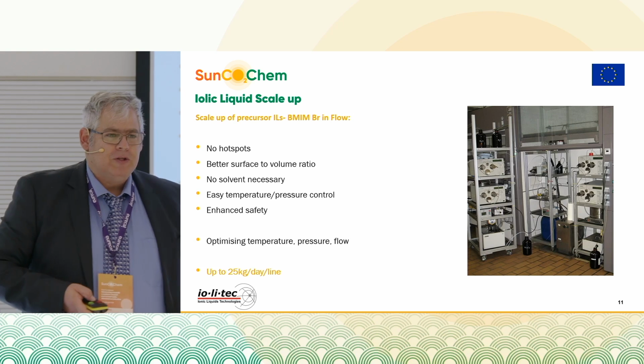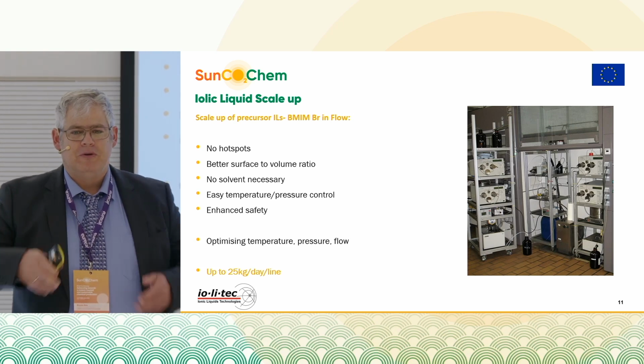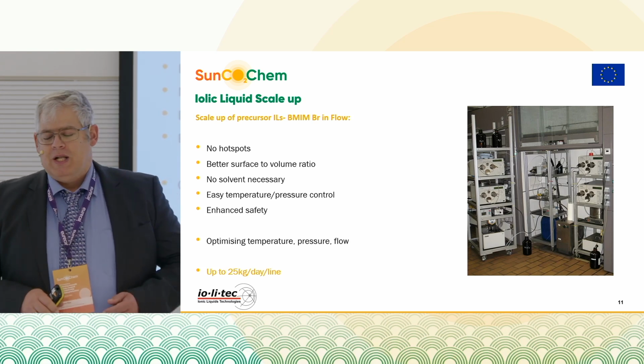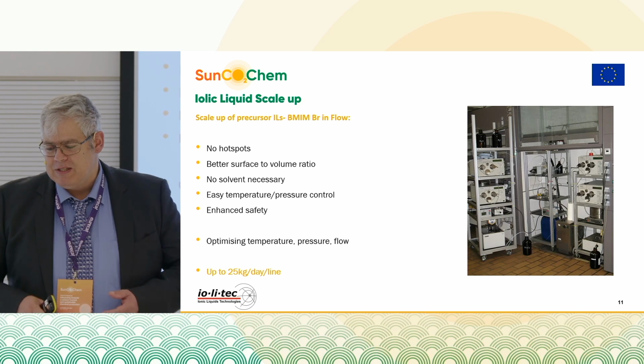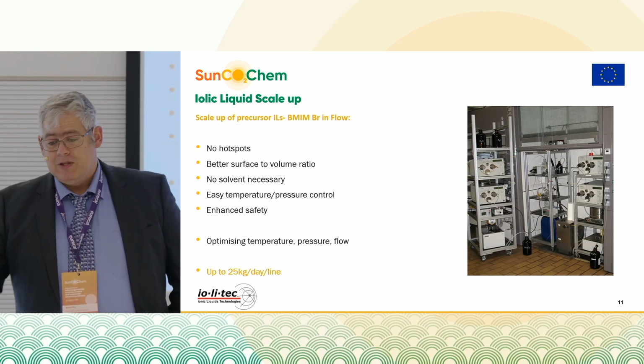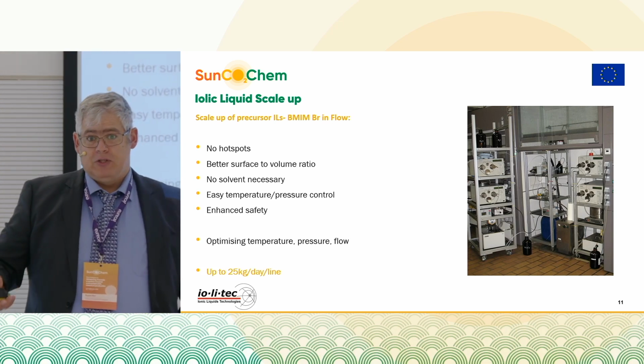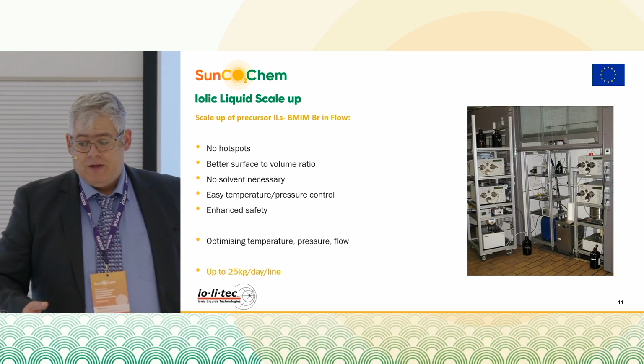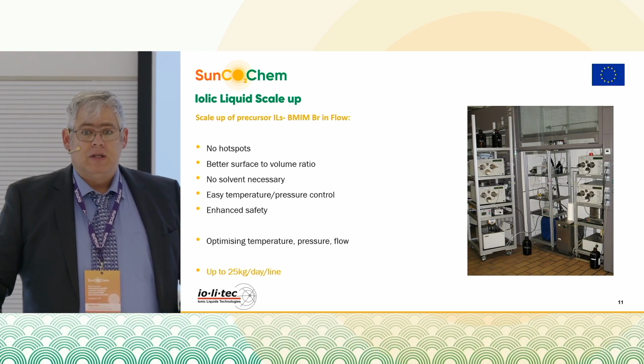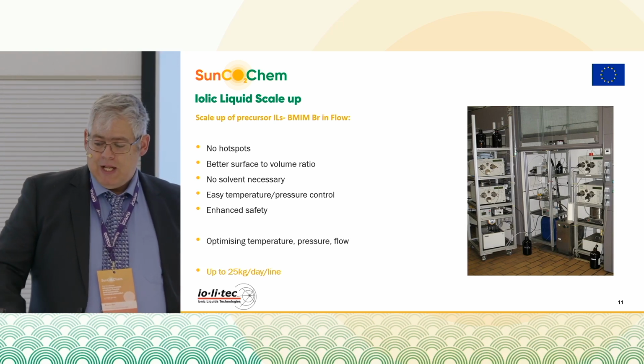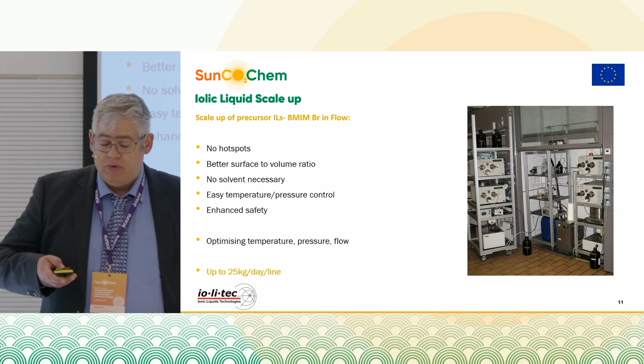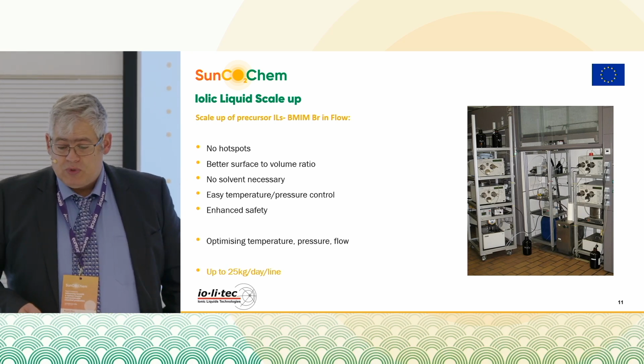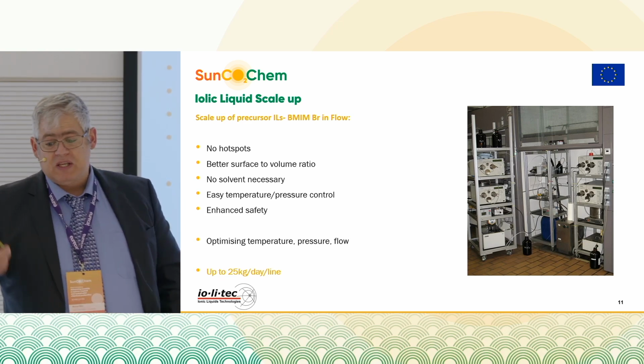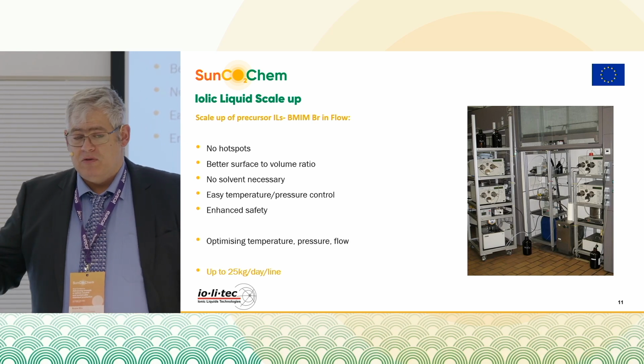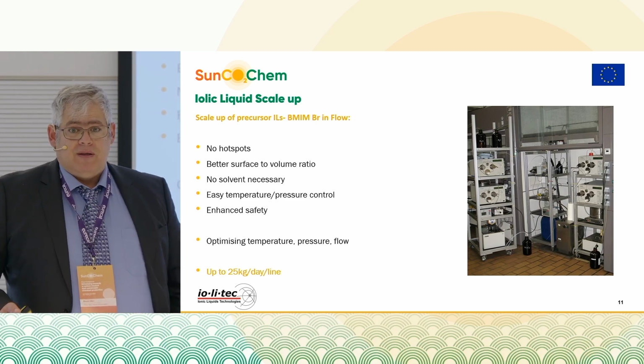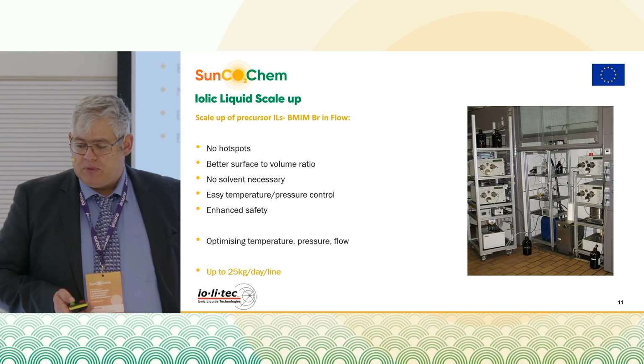The very nice thing about flow technology is that what you're doing is you're basically mixing your starting materials, you're passing them through a, let's say, reaction chamber, or in our case, this was relatively easy, a tube. And then you have your product. So you don't need solvents. You can very nicely control your reaction conditions because you have very good pressure and temperature control. Because it's one thing mixing up a 1-ton reactor. It's another thing to have mixing in a thin tube. And the product really comes really, really nice and really, really clean at the end of the day. And with that, we were able to produce the precursors for the above-mentioned ionic liquid on a range of, let's say, 25 kilos per day on a single line. So if you need a ton, you just make 4 lines, you have it in a week, and you're done. So this is actually a really nice way of scaling up ionic liquids production.